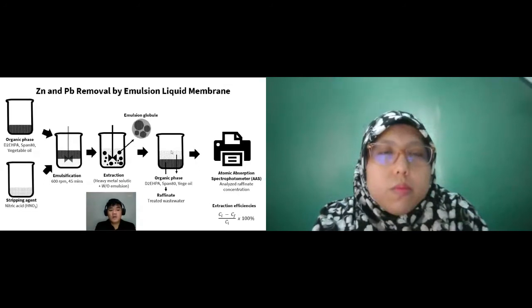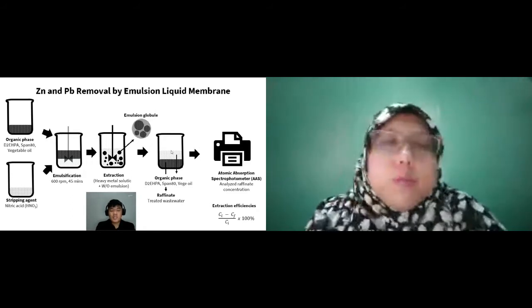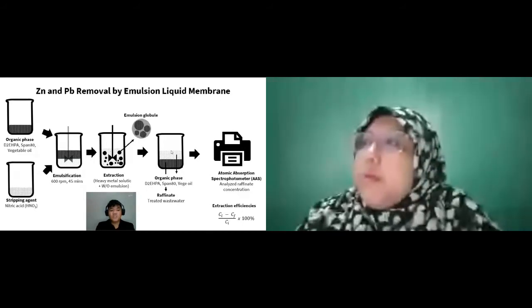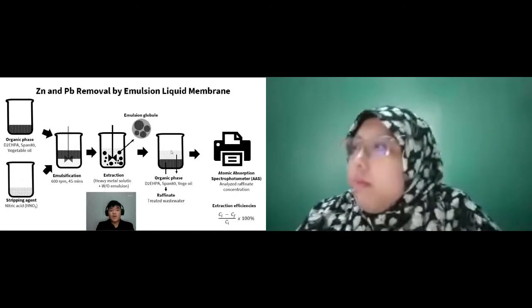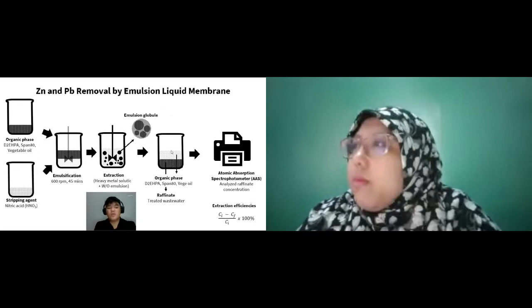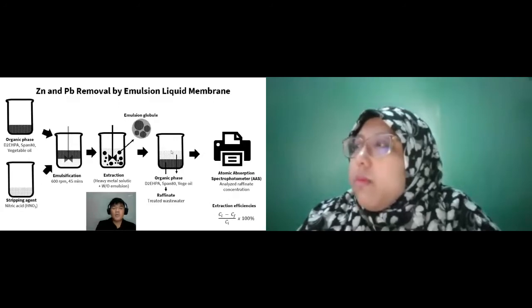So after the water-in-oil emulsion is formed, it was then contacted with 40 milliliters of external phase, which is the heavy metal solution, using a treat ratio of 2:1. The mixture was stirred at 600 rpm for 20 minutes using a magnetic stirrer to form water-in-oil-in-water emulsion. The mixture was then demulsified for 6 hours for phase separation, and the concentration of heavy metals in the raffinate was measured using atomic absorption spectrophotometer. The extraction efficiency was calculated using the appropriate formula, and the steps were repeated using different diluents.